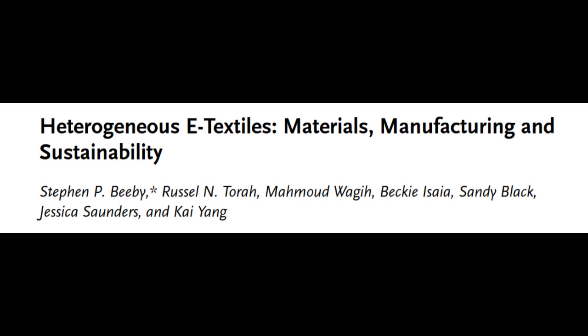Another clever approach mentioned involves using specific types of adhesives to attach components, like a UV curable adhesive. The interesting part is that this adhesive can later be softened or dissolved by soaking the connection point in a solvent like acetone, allowing the electronic components to be carefully removed, potentially recovered, and maybe even reused in another device. And studies showed components attached this way could still survive washing before disassembly. Recovering and reusing components, that's very circular.